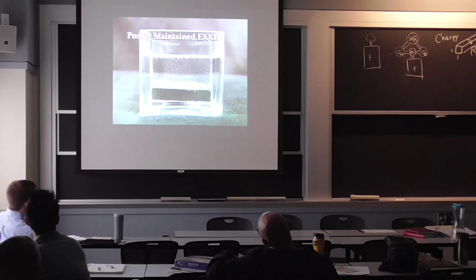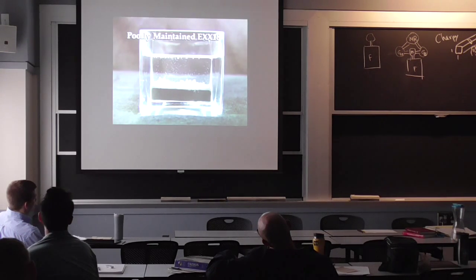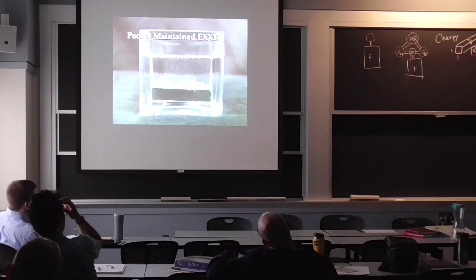The third sample was welded with a poorly maintained low hydrogen electrode that was allowed to absorb moisture. Despite the moisture-resistant coating, we can see a large number of hydrogen bubbles diffusing from the weld, similar to the amount seen in the high hydrogen electrode.